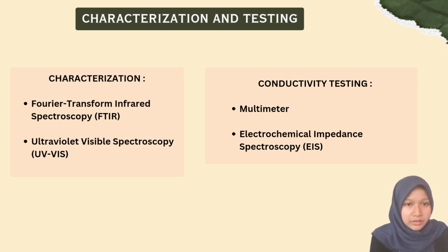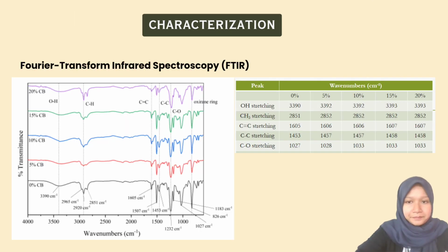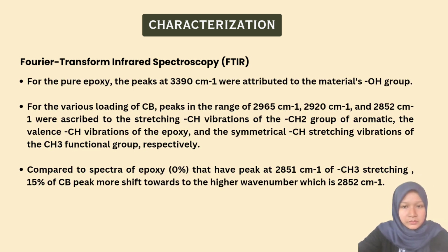For the characterization, the testing done is FTIR and UV-based, and for the conductivity testing, the testing is multimeter and electrochemical impedance spectroscopy, or EIS. As you can see in the FTIR result, they are slightly changed when the various loadings of carbon black are added. For the pure epoxy, the peak at 3390 cm-1 was attributed to the material OH group.